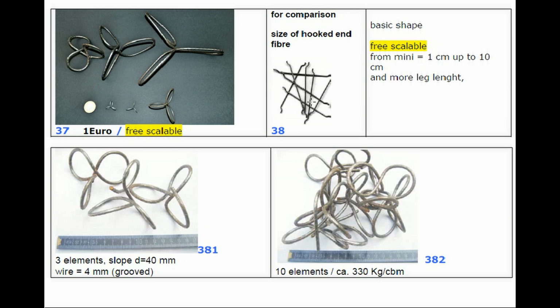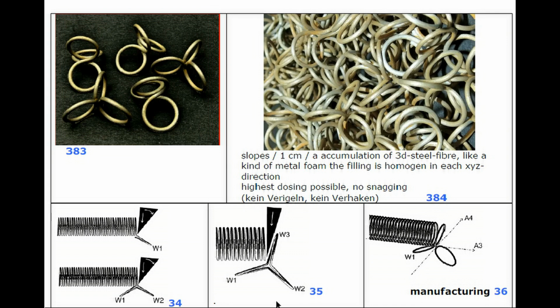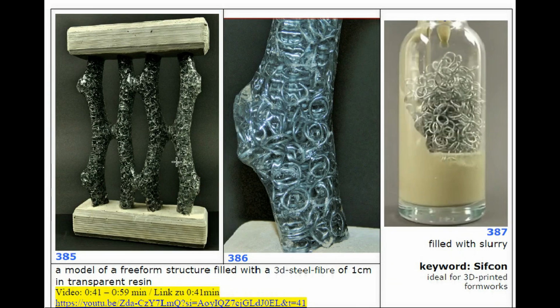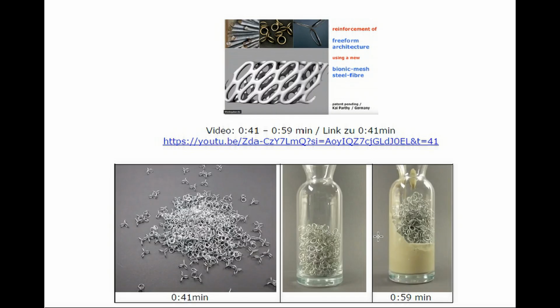In comparison, these fibers are hooked end steel fibers from the same time. Different fuse onto 1 to 3 or 10 elements, which give a concentration which is very high of 330 kilograms per cubic meter. The manufacturing is very easy and can be made at the workshop. It will be delivered as coil of wire that will be banded and cut. Some prototypes with very small diameter fibers, dense, and they can be filled with concrete slurry, keyword Sifcon. I will show you the video.